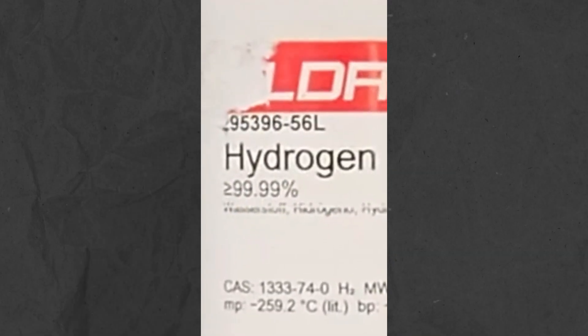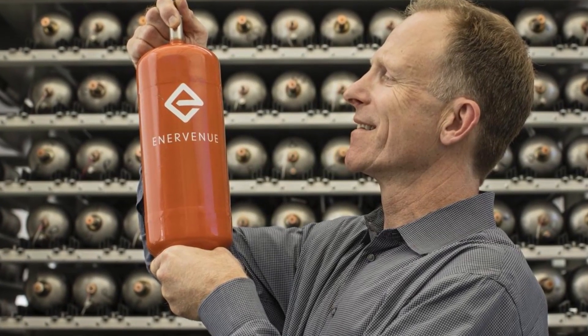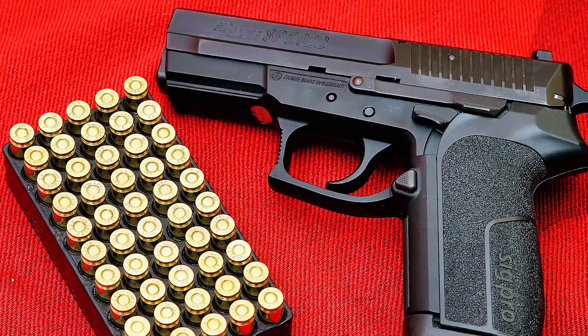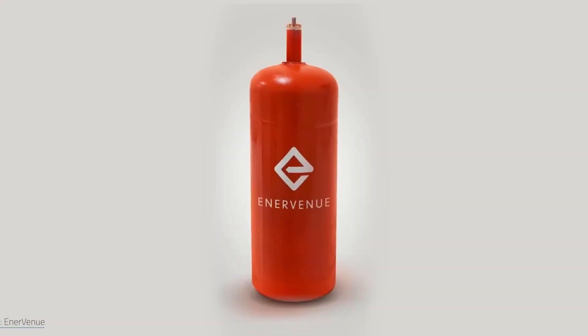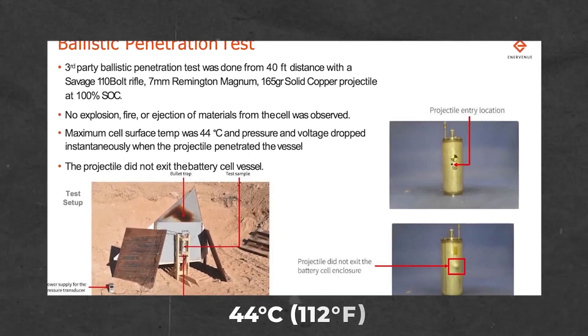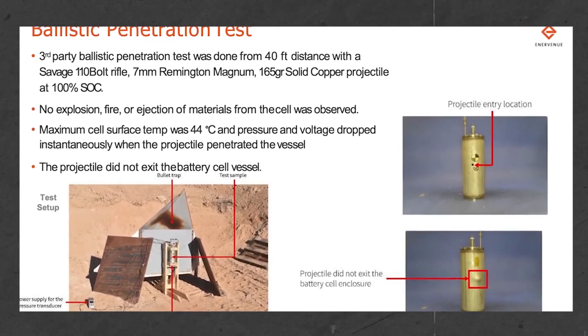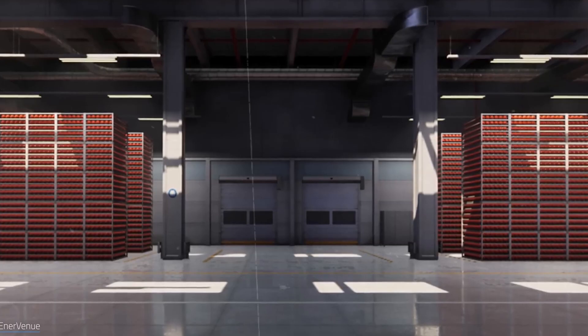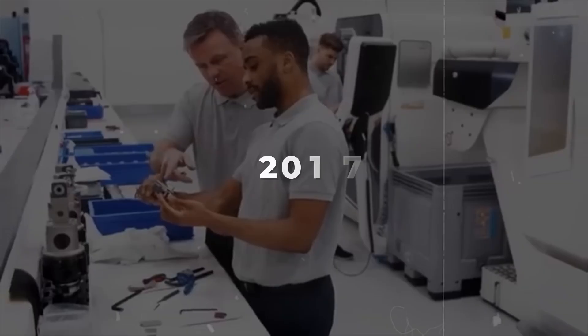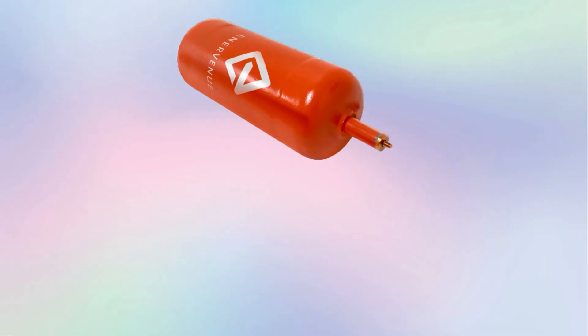With the right design, if hydrogen escapes unexpectedly, it goes up and away. That doesn't mean there's no fire risk, but handling hydrogen safely is possible. EnerVenue conducted intense tests where they deliberately poked holes in their batteries using nails and even different types of guns. There were no explosions or fires, and even the bullets didn't get launched out of the battery. The battery's surface temperature peaked at a reasonable 44 degrees Celsius (112 degrees Fahrenheit), and both pressure and voltage dissipated as soon as the battery was pierced — no explosions, no runaway hydrogen, no chance for heat or electricity to start a fire. NASA also did tests back in 2017 showing that even when hit at high speed, their nickel-hydrogen batteries didn't explode or experience any significant heat-ups.